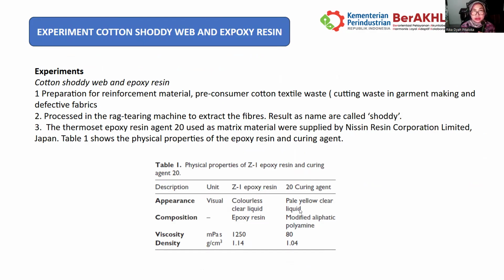Okay, so next, we are going to discuss the experiment on the cotton shoddy web and the epoxy resin. The experiment started with the preparation of the reinforcement material, which is the pre-consumer cotton textile waste. In this case, the cutting waste is taken from garment making and defective fabric. All this cutting waste is processed in the rag tearing machine to extract the fiber, and the result is called shoddy. The shoddy will be put aside, and at the same time we prepare the thermoset epoxy resin. We call it epoxy resin agent 20, used as the matrix material. This resin is supplied by Nissin Resin Corporation Limited, Japan.